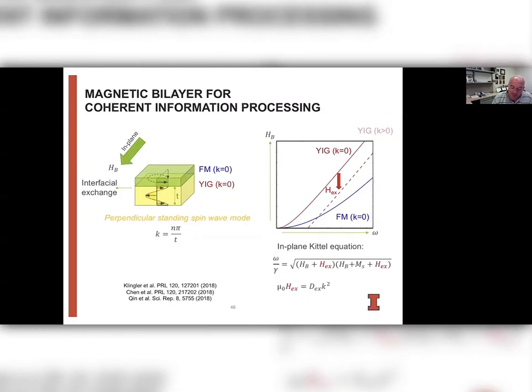Now, at the same time, we can have very specific wavelengths defined by the thickness of the yttrium iron garnet layer, so that we have only specific standing spin wave modes allowed, determined by the thickness of that layer. And so if we make this thinner and thinner, this simply means that the wavelength becomes shorter, and we get to larger wave vector transfers. So we can move the resonance further down.